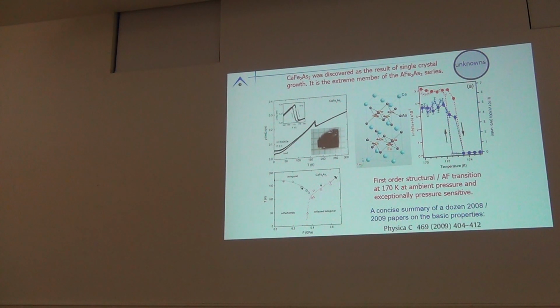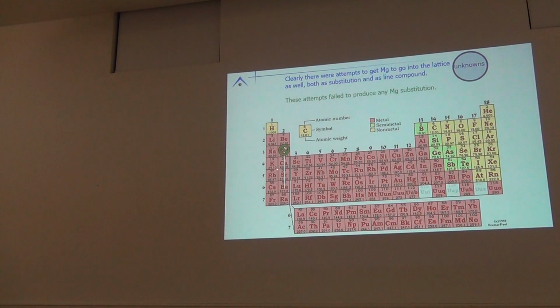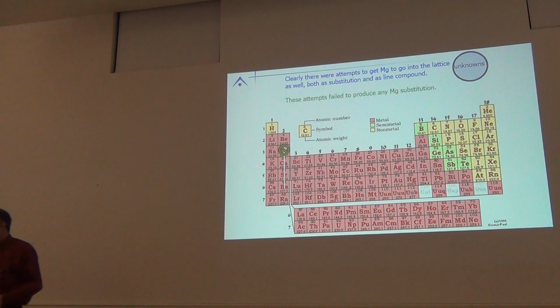Now, that's great. Calcium. What about magnesium? Well, we go up to magnesium. All attempts in our lab to grow magnesium 122 or to dope magnesium into calcium or anything else failed. I know at least 3 other groups around the world that made similar attempts. They found nothing also. So at least up to this point, magnesium doesn't seem to work, even when you try to grow it under 3 GPa's pressure. So it just doesn't like to form. Sometimes you reach the end. So sometimes you look for things and it doesn't work. All right.